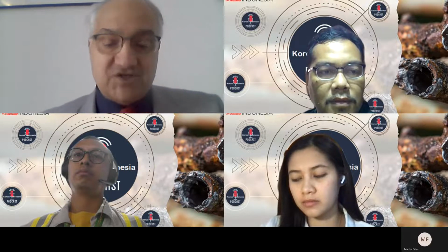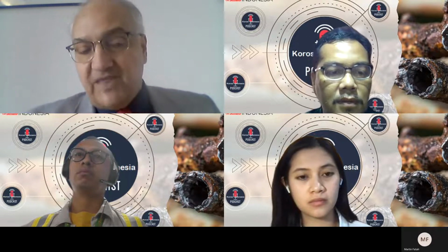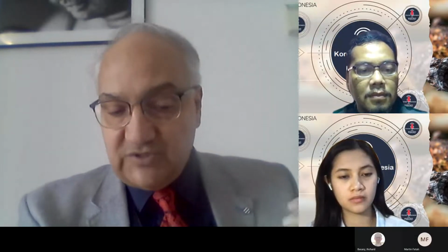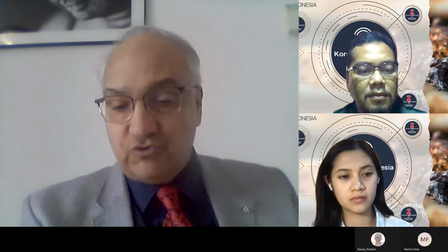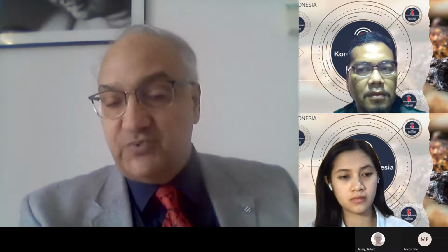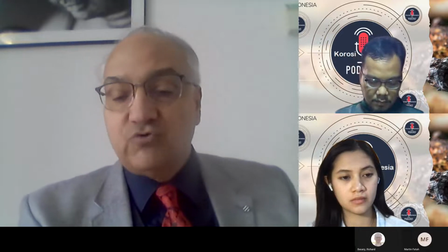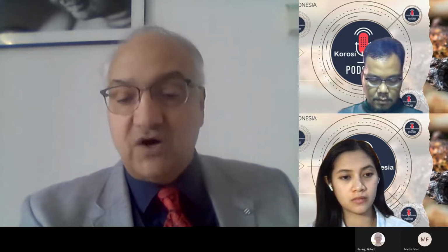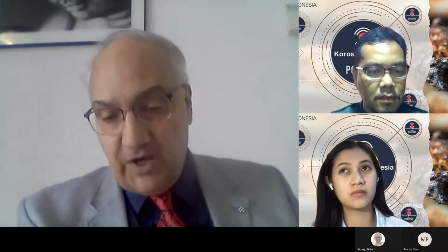Simply put, when bacteria use the electrons that are thermodynamically liberated, freed from the metal, for their metabolism, they contribute to corrosion, and we see very high corrosion rates. For example, in the case of sulfate reducing bacteria, the notorious SRB, you could achieve corrosion rates of up to 36 mpy.